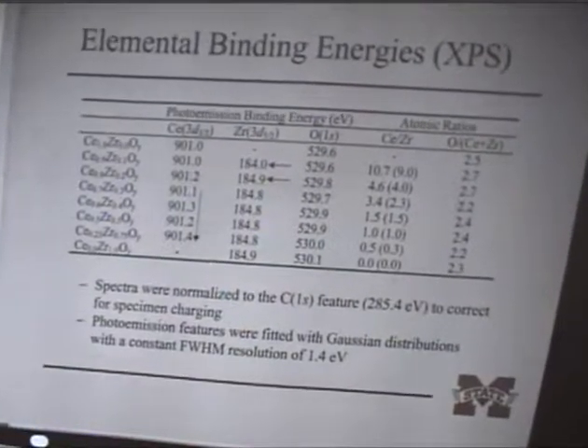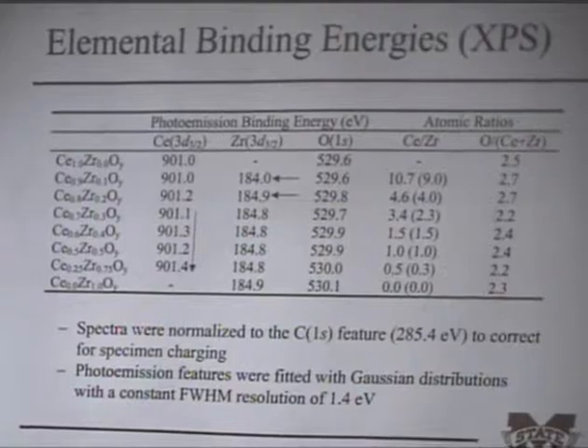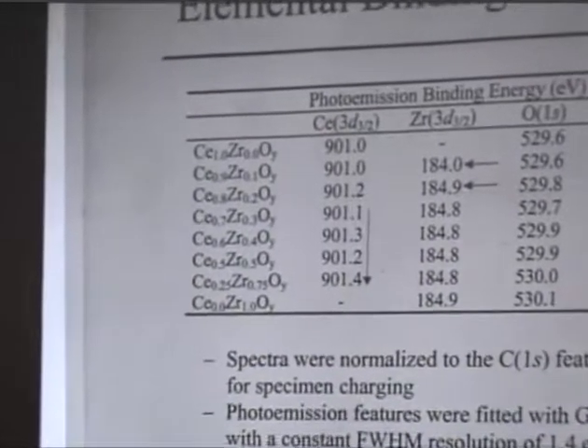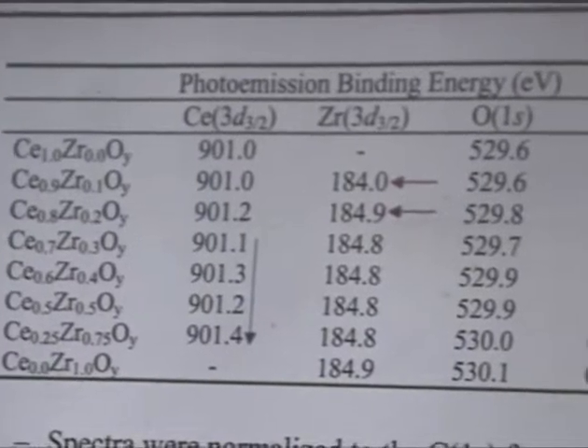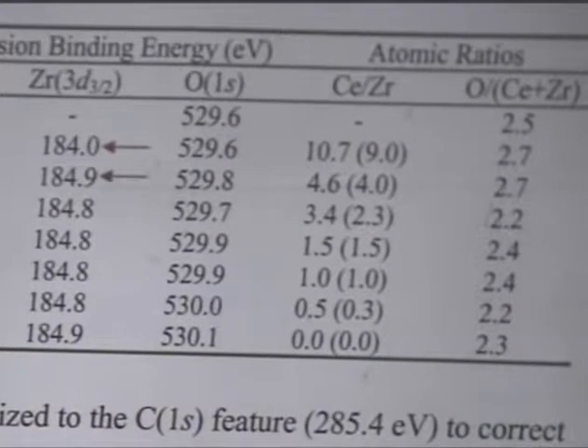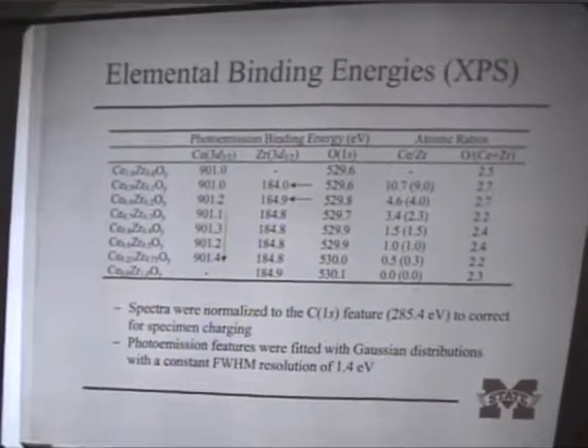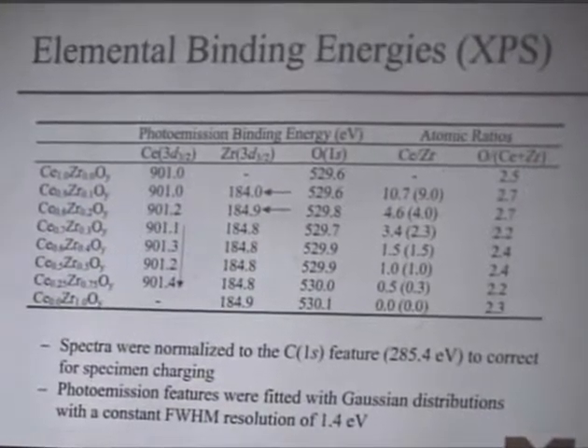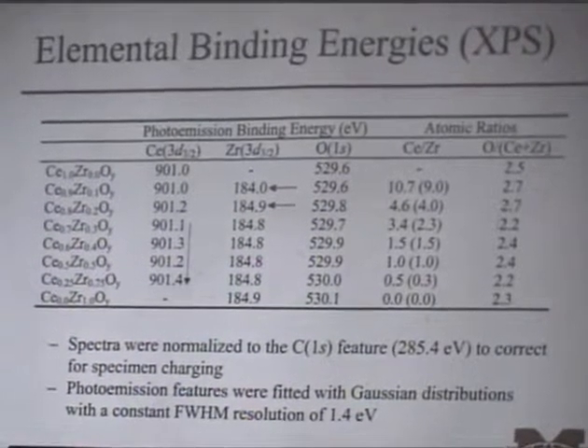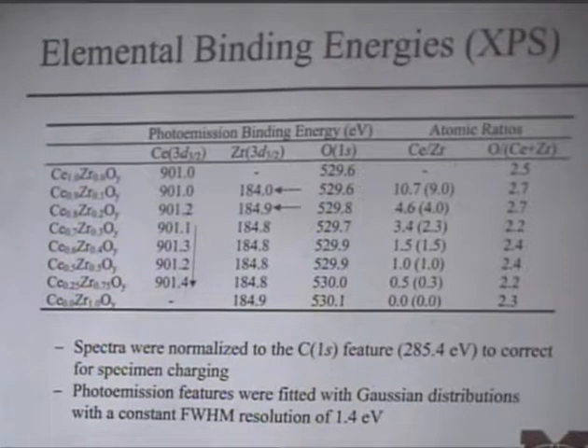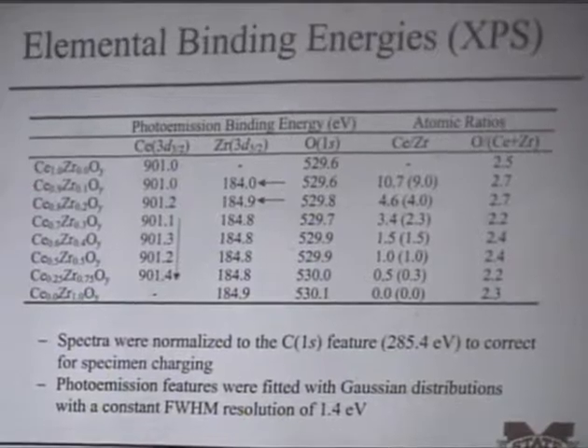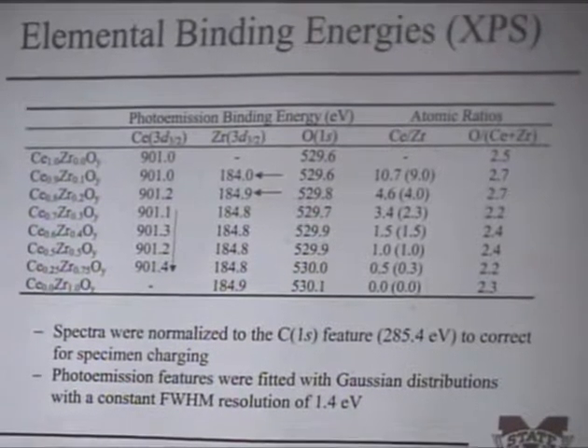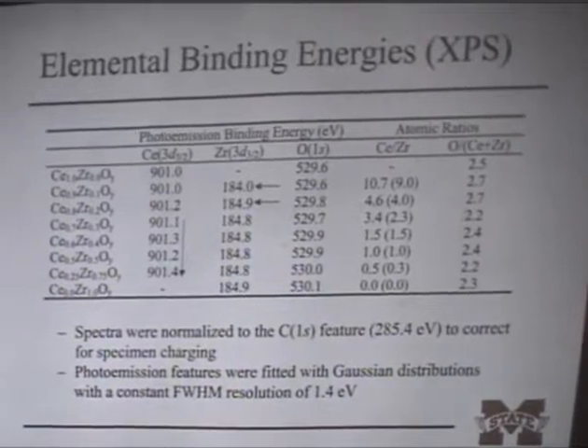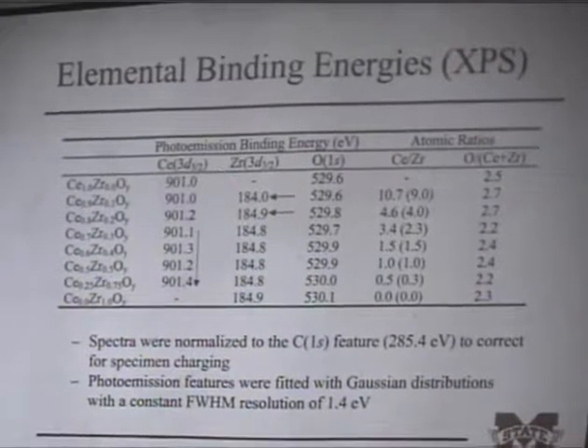We also took a look at seeing if there were any changes in oxidation state as a function of composition or preparation conditions. And we see some small shifts in the binding energies. However, none of the shifts are significant enough that we're seeing a complete change in oxidation state. If you're familiar, especially with cerium, it is always partially reduced. In other words, you always have some vacancies and things at the surface. It's very difficult to fully oxidize. By comparison with some of the single crystal work, we estimate our cerium here is what would be termed a nearly oxidized surface. So it's not reduced cerium oxide, and our binding energies tend to support this.